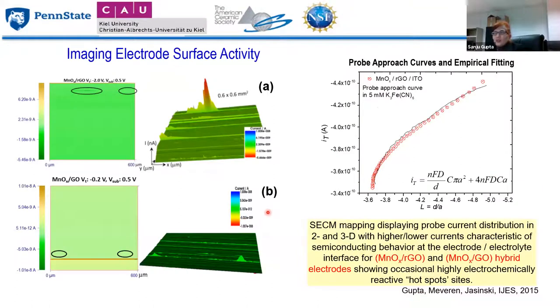And then once again, we basically use the same technique to image our electrode surface activity. And interestingly enough, as you can see here, the whole surface is not fully or uniformly activated, despite the fact that the material is deposited everywhere. And that basically started to provide us insights into how to maximize this electrochemical activity.